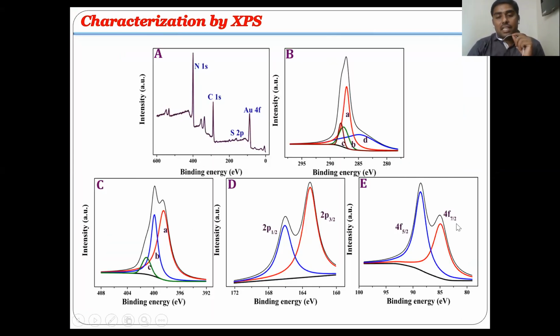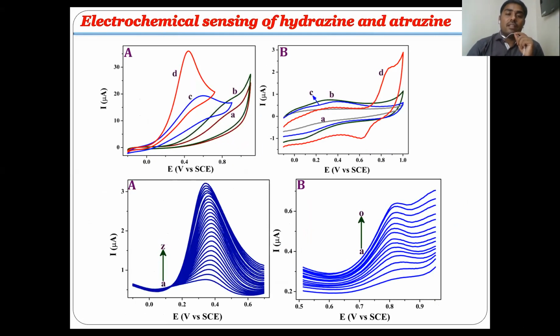XPS confirmed the sulfur doping as well as the gold nanoparticles formation on the surface of S-doped C3N4 structure. So we utilize this material for the electrochemical determination of atrazine and hydrazine, and the composite modified electrode exhibited higher catalytic activity than the individual one.